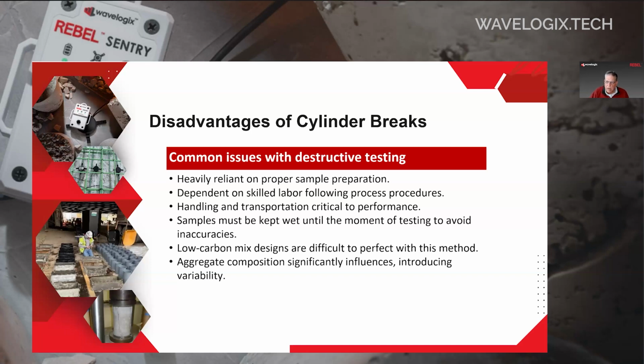Also today, we have many, many different new mix designs coming on board on ways to reduce the amount of carbon impact by reducing the amount of cement and adding in other additives. And those new mixes are finding that it's much more difficult to make accurate cylinders. Also, the aggregate composition significantly influences the way the cylinder is made and other variability. And aggregates can be anywhere from under an inch to as great as 3 inches in size. And so if you have large aggregates and you put it in the wrong type of compressive mold, you could have inaccuracies. So a lot of things can go wrong in making cylinders, and yet we use that in our operation every day to measure the strength.